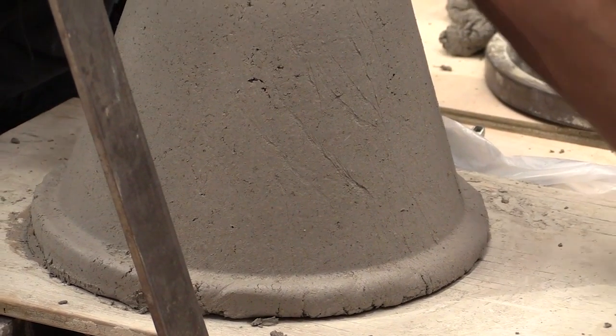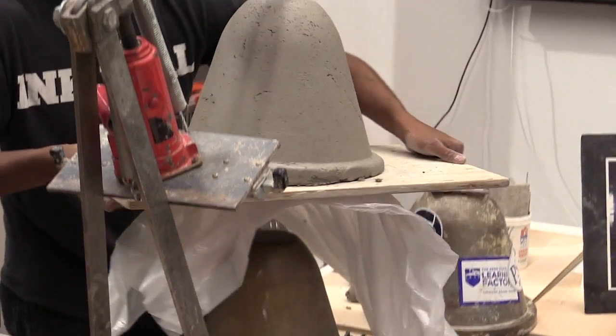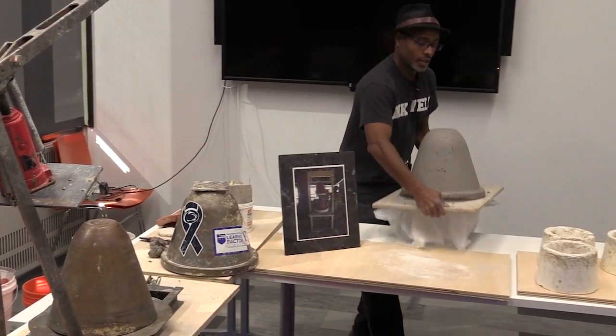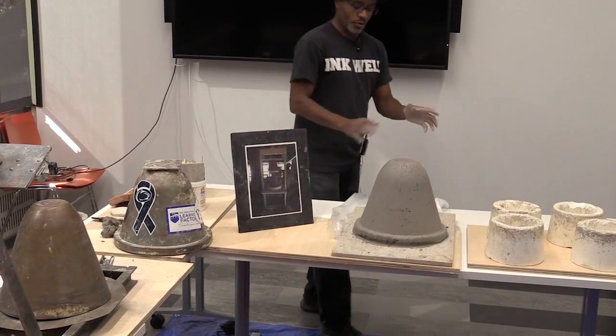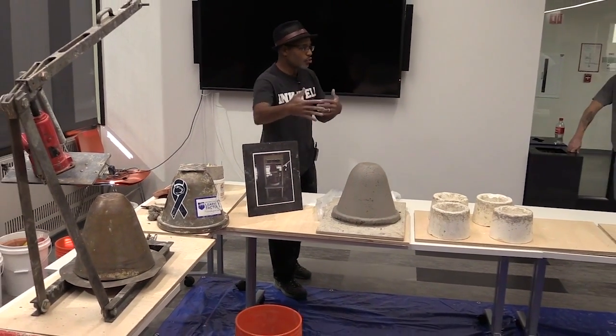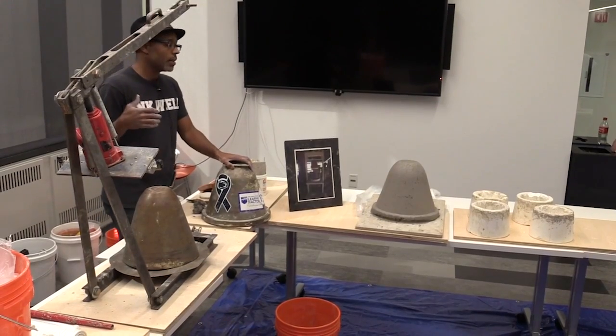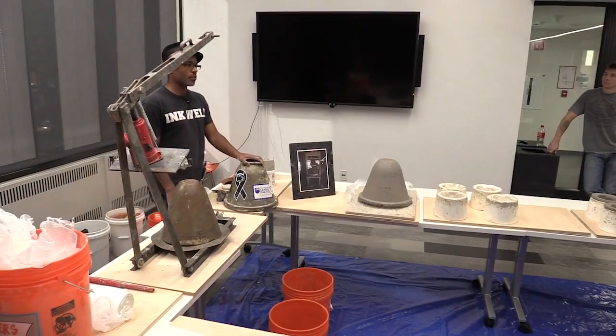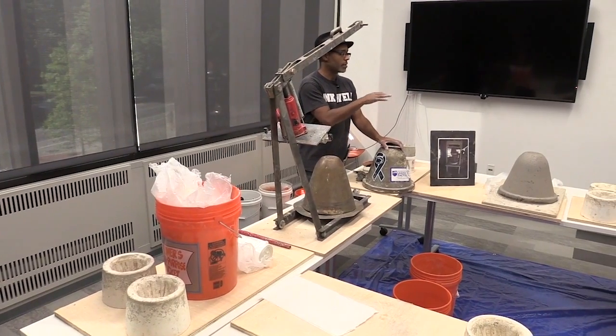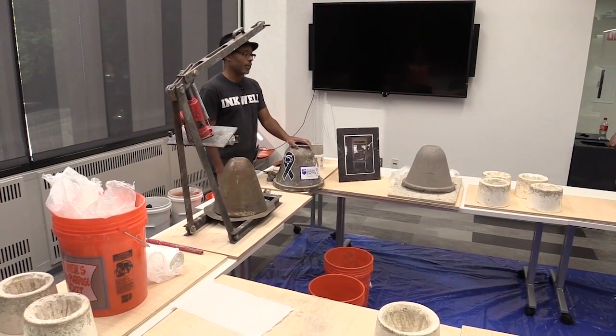Because the bat is wider than the base, I simply lift — and there's the filter. I can place this down on a shelf in the studio or facility. Another worker would clean it up, smooth up some of the edges, and stamp it with a date and a number so we can track the way it operates. We let it dry, then fire it in the kiln to about 866 degrees C. What happens then is the sawdust burns out, which creates a more porous vessel that allows the water to flow at a more rapid pace.